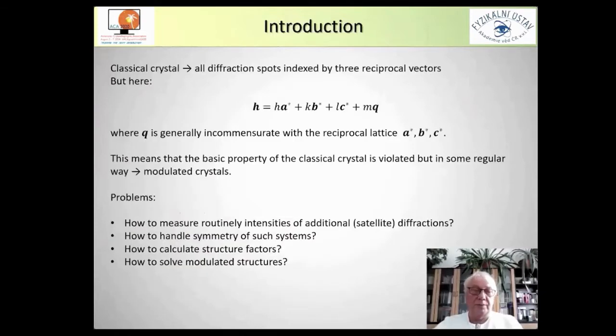All diffraction spots of classical crystals can be indexed with the three reciprocal vectors. However, for modulated structures, we need one or more modulation vectors, which are generally incommensurate with a reciprocal lattice. This means that a basic property of classical crystals is violated, but in some very regular way. The problem is how to measure intensity of additional satellite diffractions routinely.